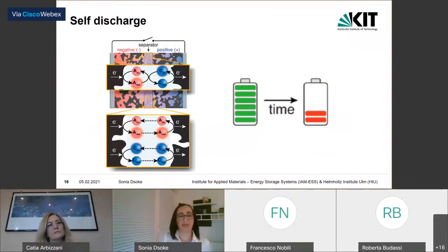Another important parameter to be checked in a supercapacitor, and especially a supercapacitor with a redox electrolyte, is the self-discharge. Normally, after you charge the battery or supercapacitor, you don't use the device immediately, but you will use it after a certain time. And we need to check how much residual capacity and energy is stored by the system after this time. What's happening when we have a supercapacitor with a redox electrolyte? We have a species which is reduced at this electrode, and the species which is oxidized on the other electrode can cross the separator and arrive at the opposite electrode, where you have the opposite reaction. Because of this crossover, we cannot keep the same capacity which is initially stored, and we then observe the self-discharge.